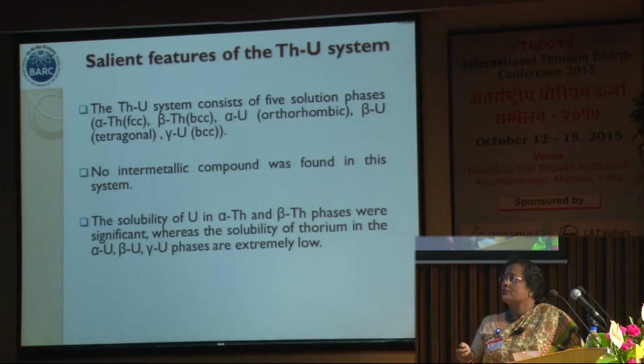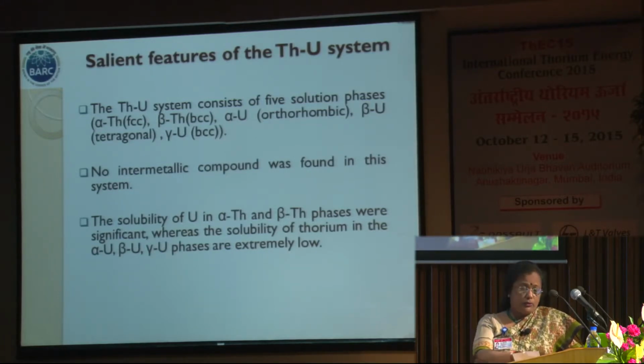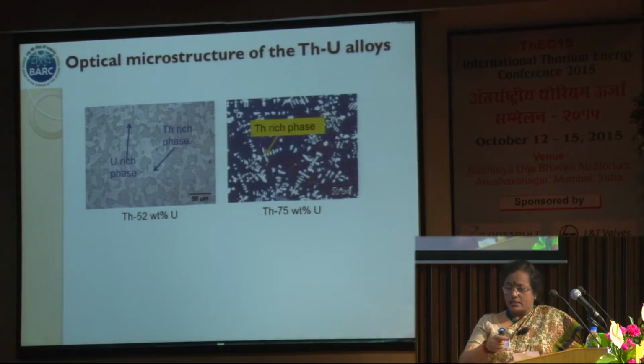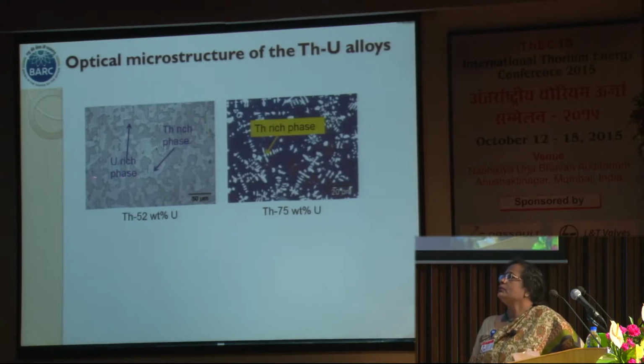The salient features Jagtap has again said, so I'm not going back to this. I just wanted to show that we have worked on the range from very low uranium to very high uranium, or you can say uranium-lean alloy to uranium-rich alloy. Here this composition is thorium 52 weight percent uranium. Here you can see that the microstructure shows they form an interconnected structure where you can see roughly 50% thorium and uranium presence.